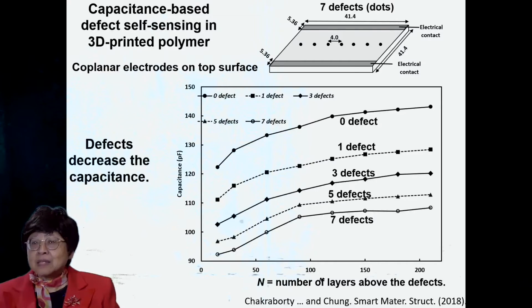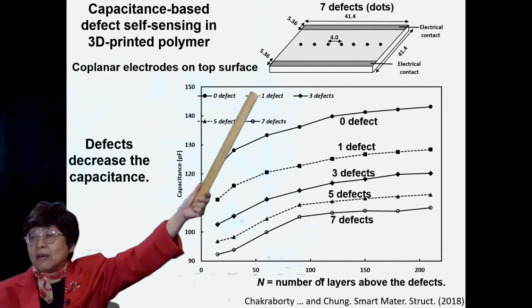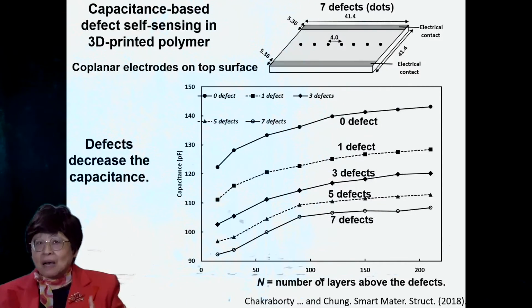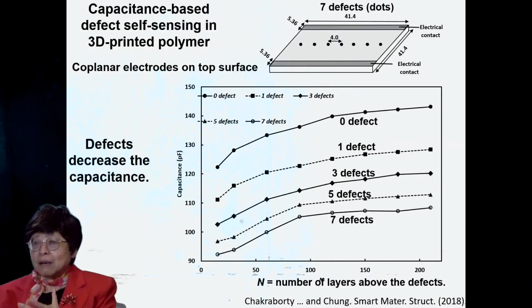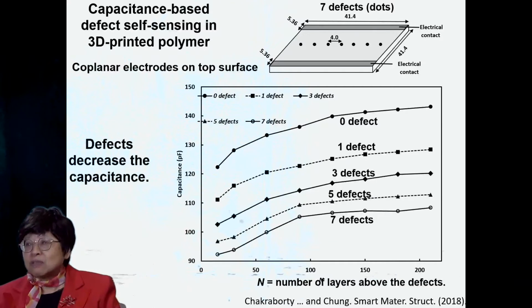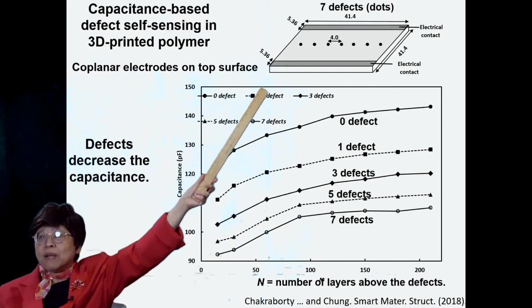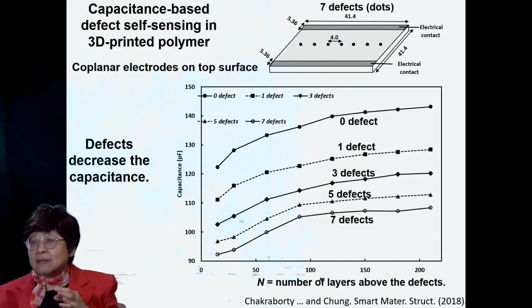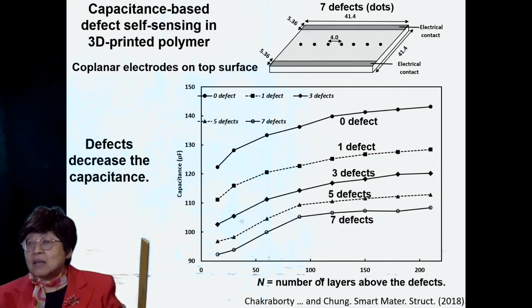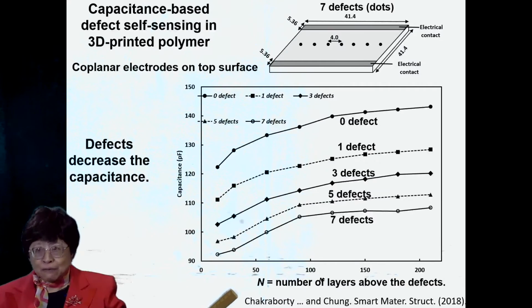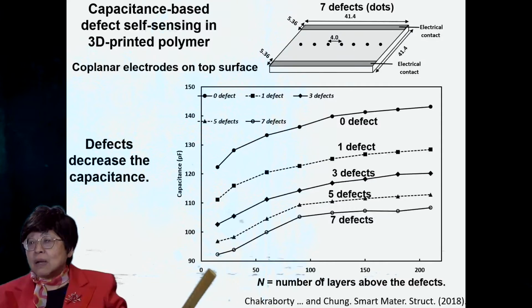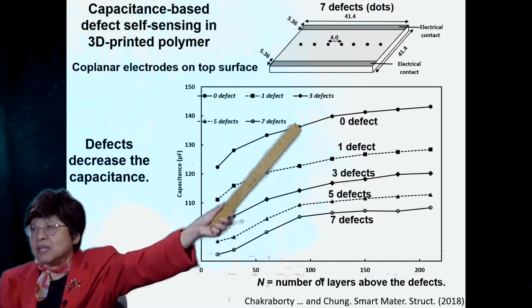The polymer, in this case, is not conductive. And we have 7 dots here, meaning 7 artificially inflicted damage, defects rather, and we have 2 coplanar electrodes on the outer surface. And the defects are positioned between different printed layers. And shown here is the capacitance versus N, which is the number of layers above the defect. Okay? So in general, consider 0 defect to 7 defects for the 7 dots.